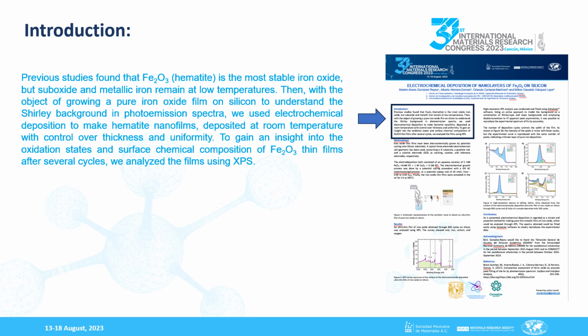Previously, we found that iron-3 oxide, or hematite, is the easiest and the most stable oxide to obtain. However, with the electrochemical deposition, some pure metallic iron and other suboxides remain after low temperature annealing. On the other hand, higher temperature annealing causes a chemical reaction with silicon and the formation of protrusions.